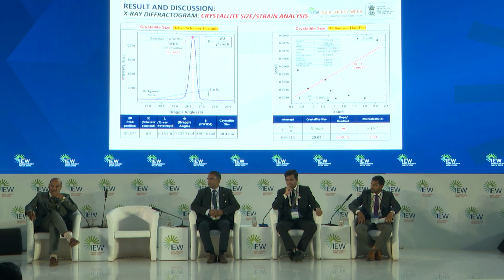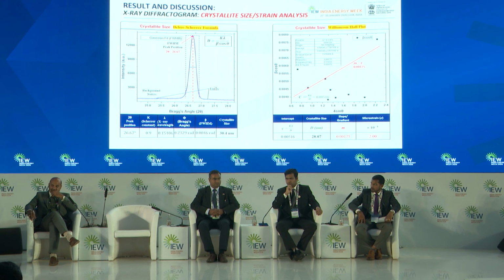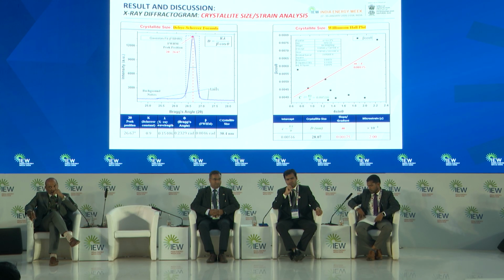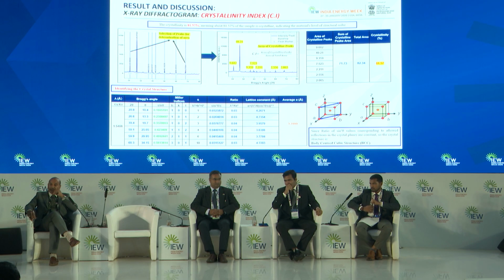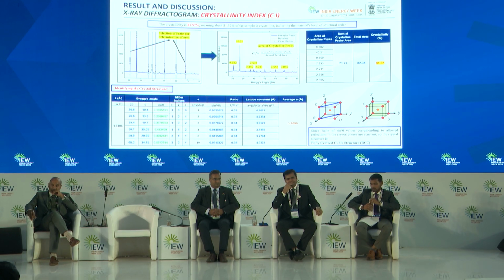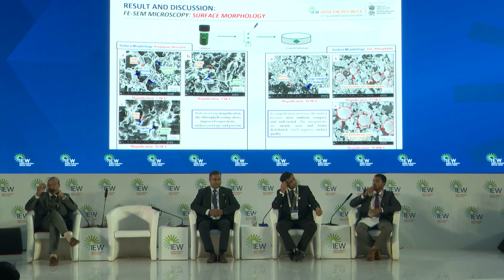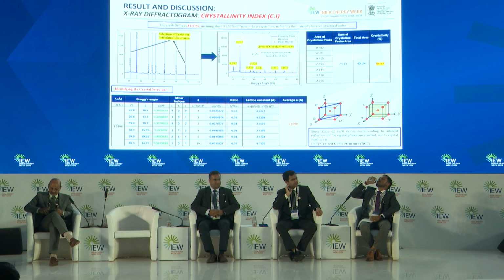Again, when we went for the Tauc plot, it showed a reduction of the band gap from 2.41 electron volt to 2.2 electron volt. And for solar fabrication, it is reported that if the band gap lies between 0.7 to 3.2, we can go for solar cell fabrication. So XRD again confirms the crystallinity, right?